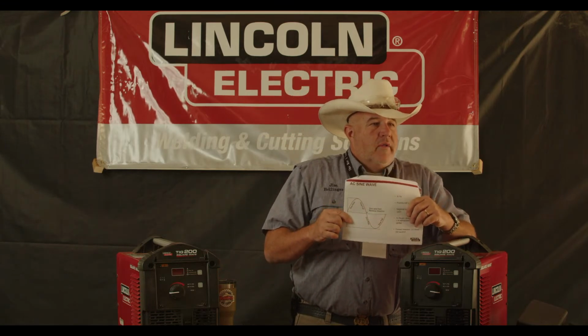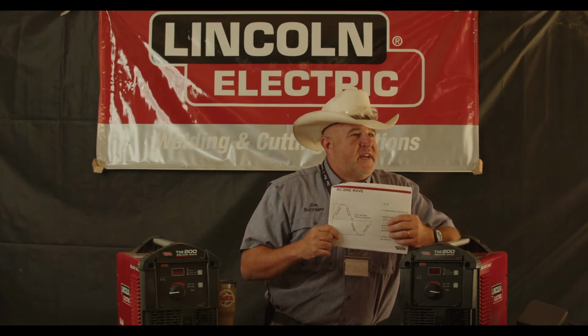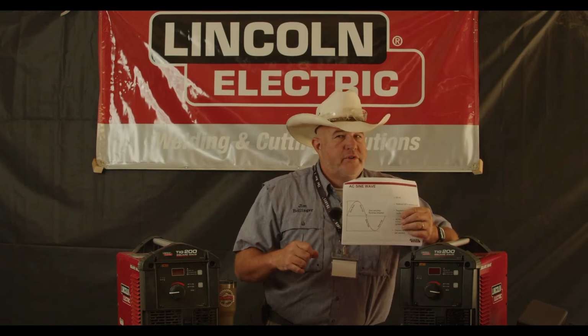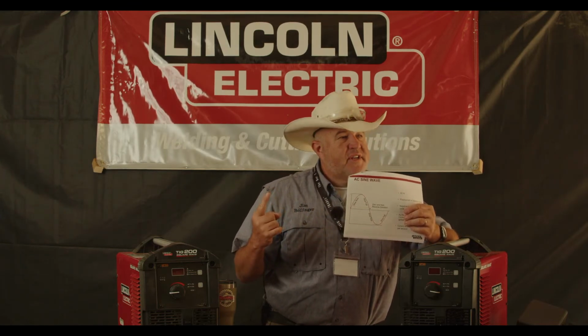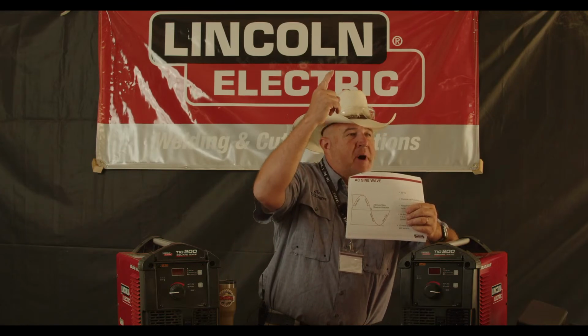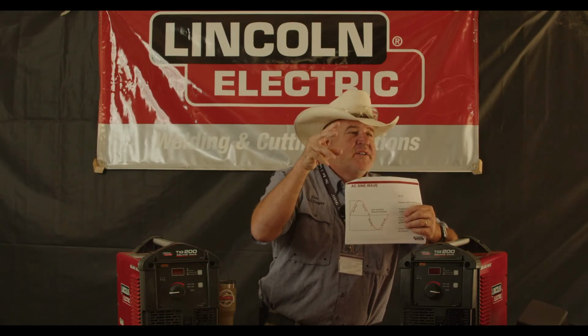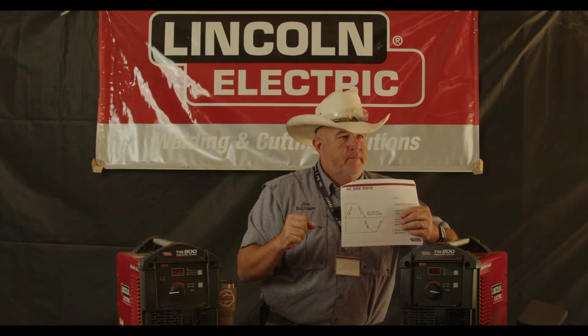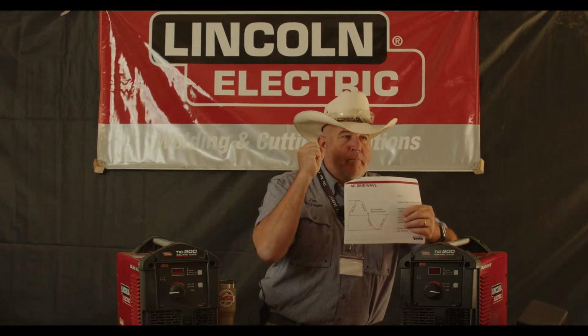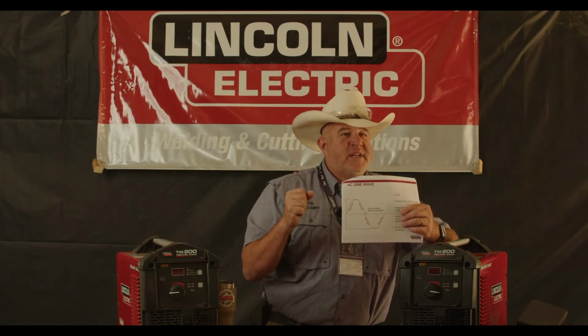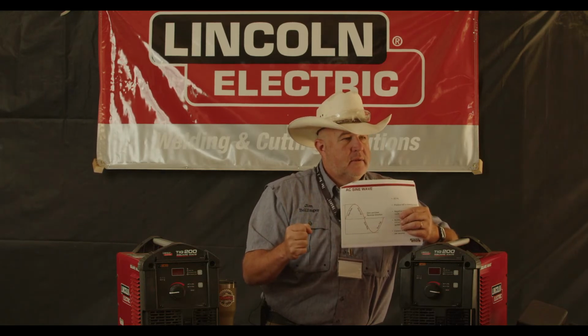Okay. The Linde Corporation, when they figured this out pre-World War II, what they figured out was that the sine wave, as it starts to go to positive, will blast the oxide layer off the aluminum. Now why, if we're blasting it all off electrically, why does it not oxidize back?